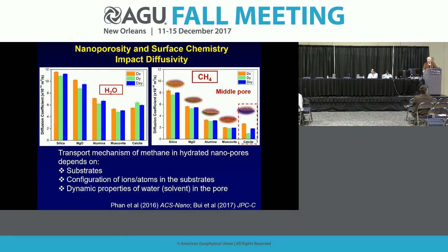Finally, I just want to talk about diffusivity. This is another take-home message. There's no time to set these calculations up to describe to you. But again, under reduced dimensionality, we have reduced diffusivity. So if you look at bulk water on this panel here, we're at about e to the minus 10 meters squared per second. For a bulk system, we'd be up around 2.5, actually way off scale for water. Of course, it changes as the surface changes.